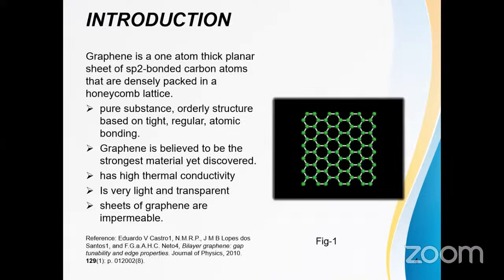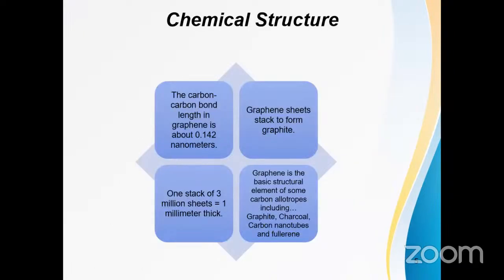Graphene is a one-atom thick planar sheet of sp2 bonded carbon atoms that are densely packed in a honeycomb lattice. Graphene possesses a unique combination of properties and has attracted attention for electronic applications. It is patternable, scalable, and has demonstrated high mobility and even room temperature ballistic transport. It is a pure substance with an orderly structure based on tight, regular atomic bonding. Graphene is believed to be the strongest material. It has high thermal conductivity and is very light and transparent. Graphene sheets are almost impermeable. The carbon-carbon bond length in graphene is about 0.142 nanometers. Graphene sheets stack to form graphite, and one stack consists of 3 million sheets and is about 1 millimeter thick. Graphene is the basic structural element of some carbon allotropes, including graphite, charcoal, carbon nanotubes, and fullerene.